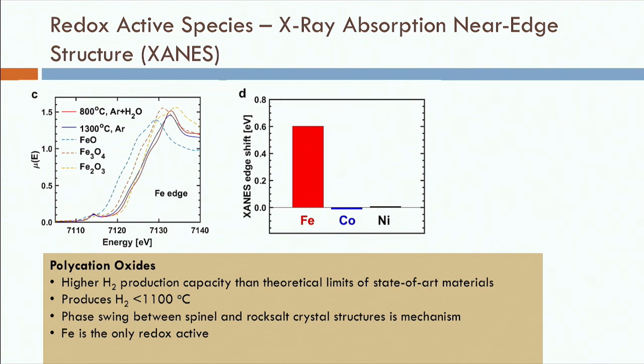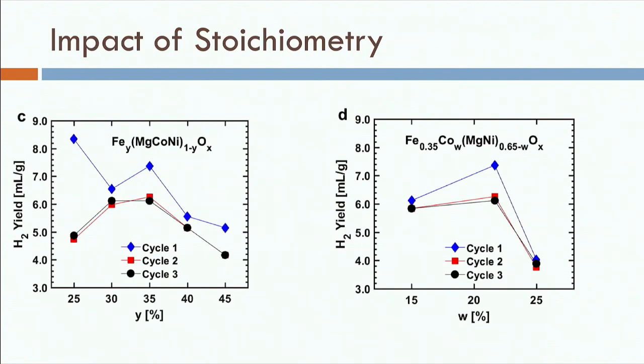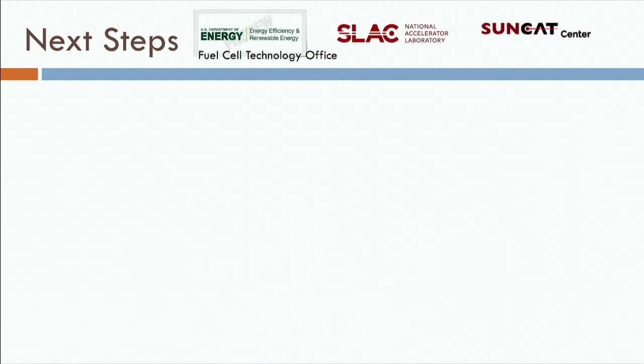Since iron is the redox active species, the question is, is there an optimal concentration of iron? And indeed we find that 30 to 35% of iron in this material seems to be working really well, thus producing these amazing results. And cobalt really doesn't change much because it's not redox active. This work has been funded by the DOE, Office of Fuel Cell Technology, a little bit of money from SLAC, and a little bit from SunCat.